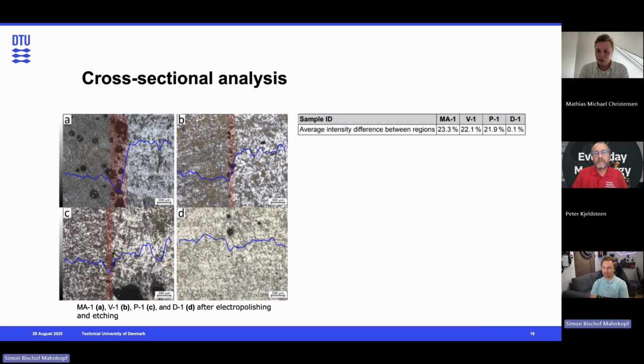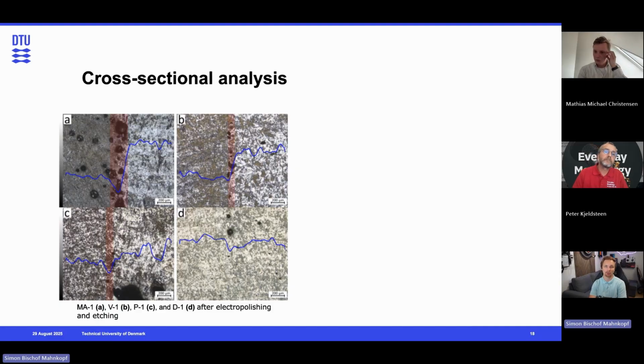And what we actually found was, if you see here, these were some cross-sectional pictures we took with light optical microscopy. And we had used an etchant here, which was a coloring etchant called Beraha, which colors martensite but not austenite. So you could get a visual contrast and a quick way of seeing whether we actually get a phase difference. And we could also use the grayscale intensity to try and measure if we actually had a difference between the phases, so it's the difference in how dark the areas were. And so what we tried looking at was using three parameters, scan speed, hatch distance, and power, in order to see what the interfacial sharpness would be between the two phases. So we used a sigma 3 threshold for the grayscale intensity, and we defined that as being the interfacial width. And in most applications, you want that in functionally graded parts to be as small as possible, as tight as possible.